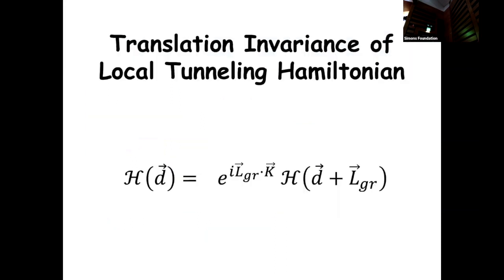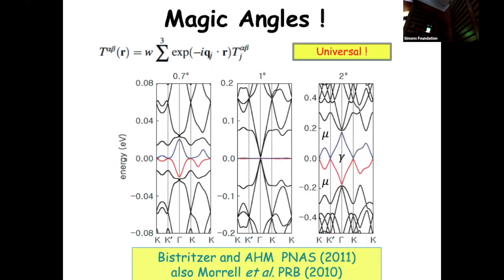We can go through the same kind of argument to build a model of the low energy electronic structure. In this case, there's a slight twist, because if I translate, for example, the top graphene layer relative to the bottom graphene layer by 1 lattice constant, it turns out that the dominant way in which the 2 layers modulate each other is by electrons tunneling back and forth. And because of that, when you translate by 1 period of the Moiré pattern, you get a phase factor in the tunneling Hamiltonian, which is easy to accommodate.